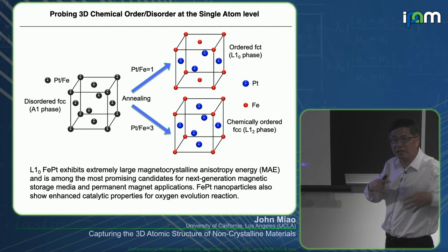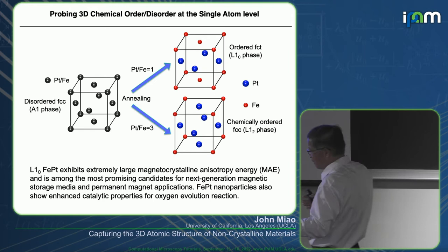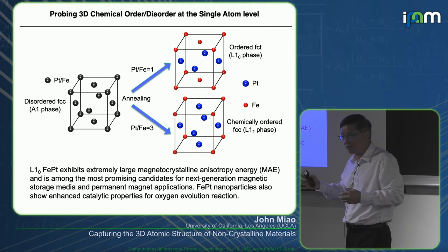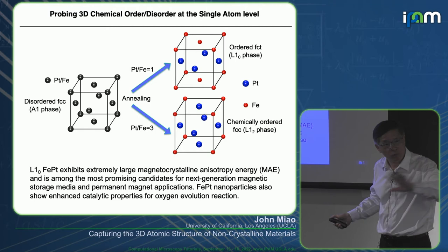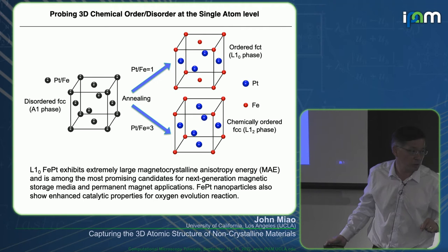And Paul mentioned disorder, glass, metallic glasses, kind of, right? So we do one step with a chemical disorder. Okay, this is chemical disorder. We work on the material called iron platinum. So iron platinum, when synthesized, forms what is called a disordered FCC structure, chemical disorder. You don't know which atoms are which. So it is chemically disordered, structurally ordered.